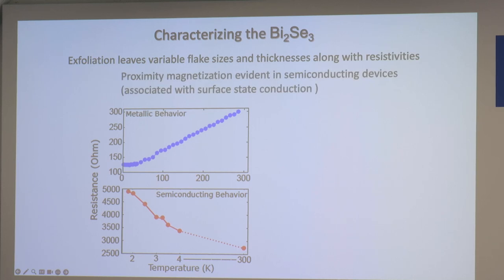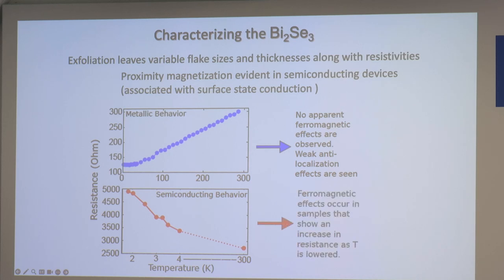What we found is that we get stronger proximity. Oh, sorry, let's go the other way. Sorry, this is the bulk in this case. It's metallic, and this is where the bulk freezes out and you have the surface states. And we saw proximity magnetization only in the semiconducting devices. So when we saw metallic devices, we didn't see ferromagnetic effects, and when we had semiconducting devices, we did. So we associate these with where we have surface state conductance dominating.